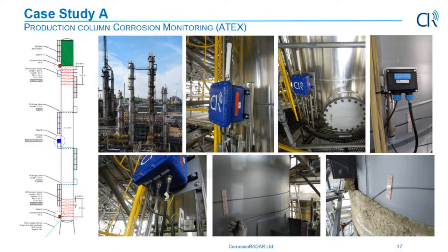So the objective here is, if so far we have not detected corrosion on this or even moisture, it looks like the insulation companies have done a very good job. But over time, if water starts to ingress, we will detect it. And at that point, the customers will decide whether this is to be inspected in the next few years, early or later. If there's no water ingress, then they will actually postpone the regular time-based inspections to the time when this is to be done, say maybe a 10-year cycle.